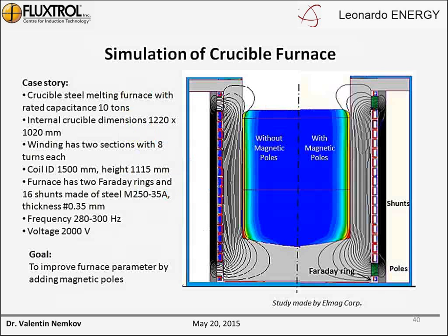And finally, I want to mention one interesting study that we made for a crucible furnace for melting steel. This is a very mature technology and a very competitive area, and it looks like everything is done. You can do nothing more there. Together with the company Elmag Corporation, we made a study for a real induction coil of 10 tons, working at a frequency of about 300 hertz, and this coil is made of two parallel sections, and the voltage is 2 kilovolts.